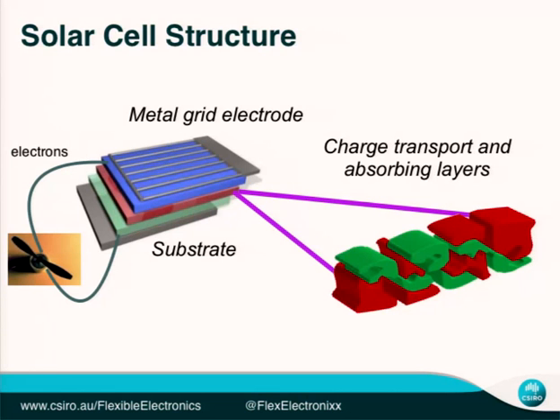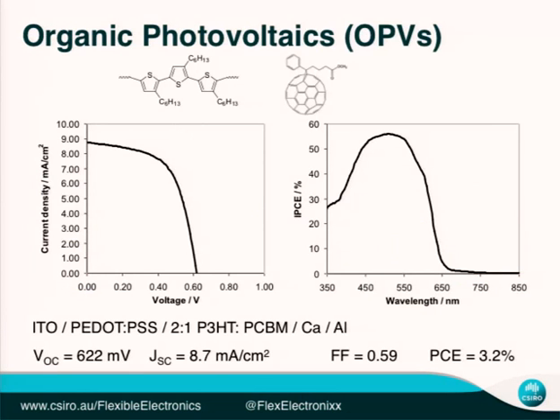So just to give you an idea of how these cells perform, this is the P3HT, the polymer shown at the top here, a polythiophene polymer, is the most commonly studied material, and this is what we sort of use to check ourselves against. And so this will give an efficiency of about 3%, but this is what the voltage and absorbance properties look like. So out of a single cell, we get about 0.6 volts, and we're absorbing light out in the sort of green out to red region of the spectrum.